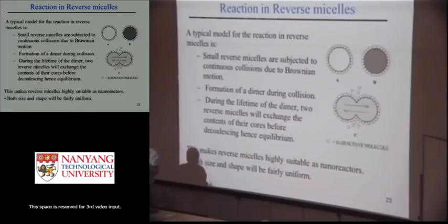One, I have some water mixed with oil. Before I put the water into this oil, I first dissolve A into the water. Then this water will mix with oil and I add some surfactant. I maybe sonicate it for some time, then magnetically stir it for some time. They will form this microemulsion. Okay, the typical procedure is that you add a small amount of water, a large amount of oil, and surfactant. You just magnetically stir it for maybe half an hour. You will get droplets of water in the oil reservoir.